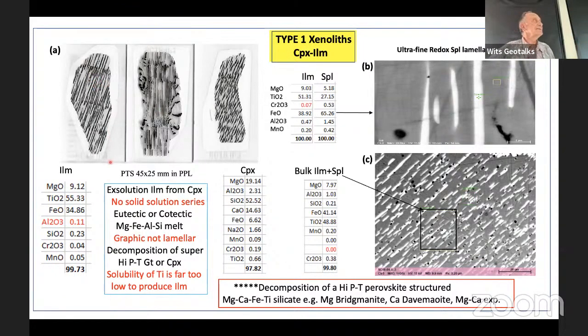Well, let's go to the theories. It appears to be exsolution. Not only that, there's a coherent relationship between the ilmenite and the clinopyroxene. It's 001, again, 100. So there is this relationship. But Joe Boyd and a lot of other people have attempted to homogenize these. Ian McGregor was another one. Absolutely no way, Jose. You cannot homogenize it into a single material. So it's not a solid solution series.